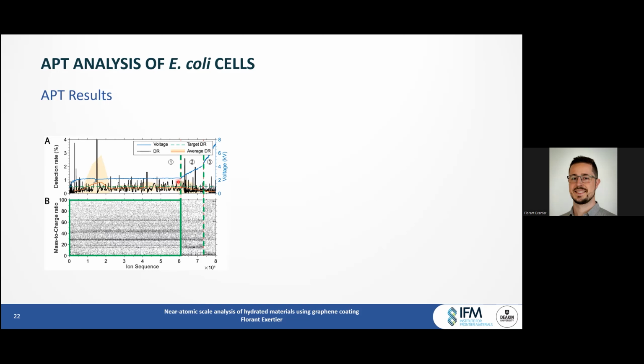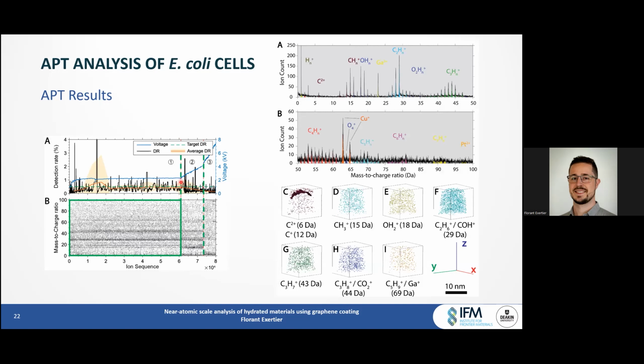So this is the mass spectrum from this part of the data, and we see many peaks up to 90 Dalton that were detected. And these can be grouped into families of organic molecular ions with varying number of carbon atoms. So here we have C4 group, C5, etc. And besides the organic ions, all of the ions that were identified earlier as being part of the signature of graphene encapsulated water, so including carbon and also water, were detected.